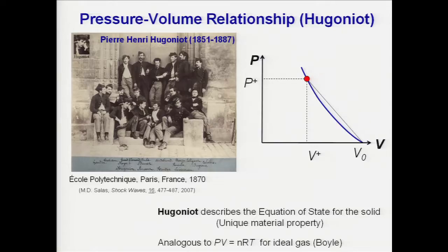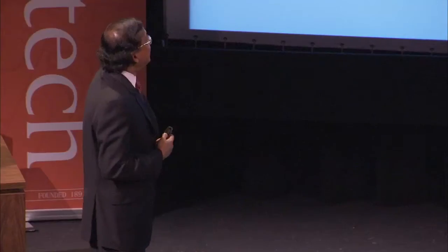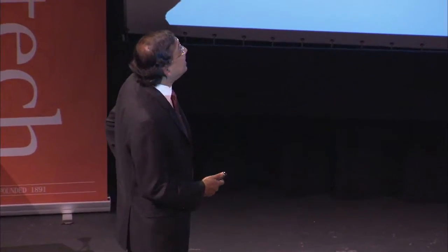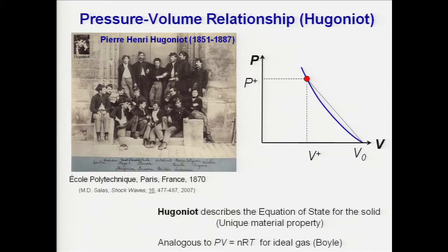So now we need a pressure-volume relationship, and that's what distinguishes different materials. This pressure-volume relationship for a solid at these high pressures is described as the Hugoniot. And Hugoniot was a graduate of Ecole Polytechnique in Paris, in France. And here is the picture of Hugoniot when he was a student at Ecole Polytechnique in 1870. And here he looks disinterested in the whole thing. But later on, he came up with this brilliant idea of the conversion of the kinetic energy into the potential energy when you have shocks. And he derived this relation for the pressure-volume relationship. So on this curve, when you increase the pressure, the volume becomes small. This is a unique signature of the material, and it is what one is interested in for most engineering applications. You want to know this relation. It is similar to an ideal gas, for example, where the product of the pressure times the volume is a constant, what's called Boyle's law.